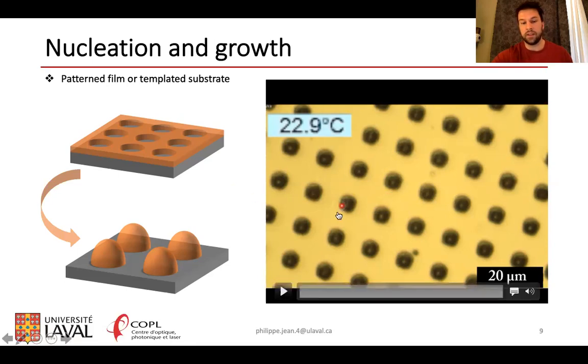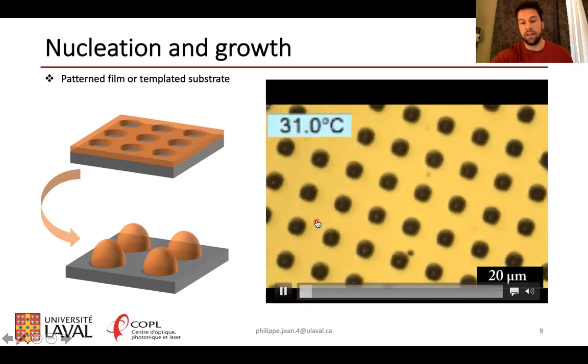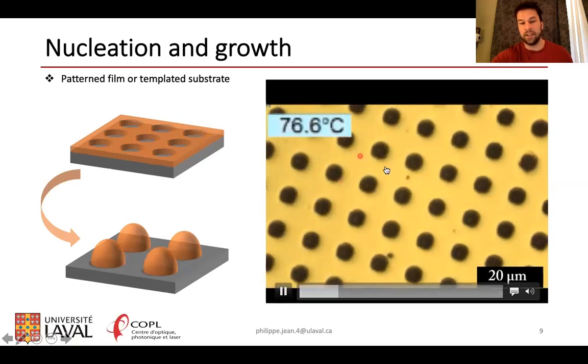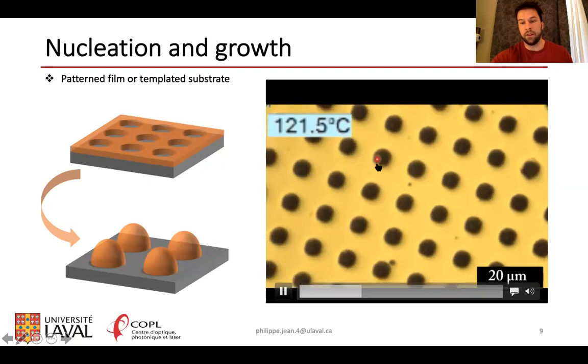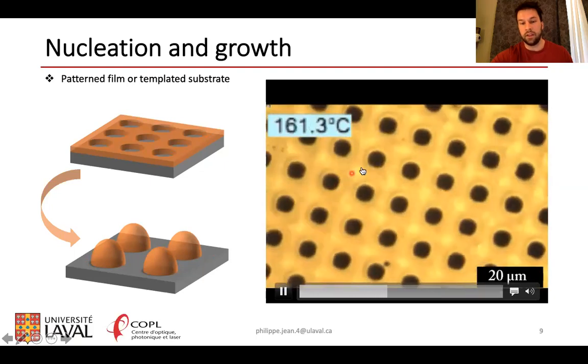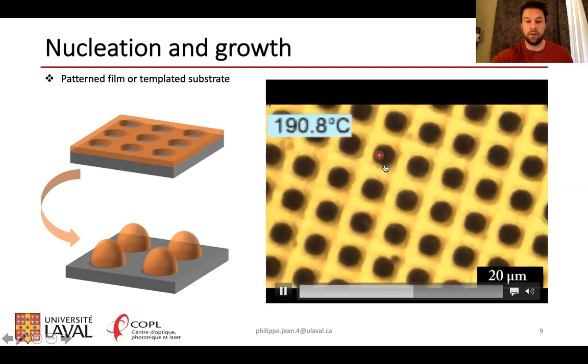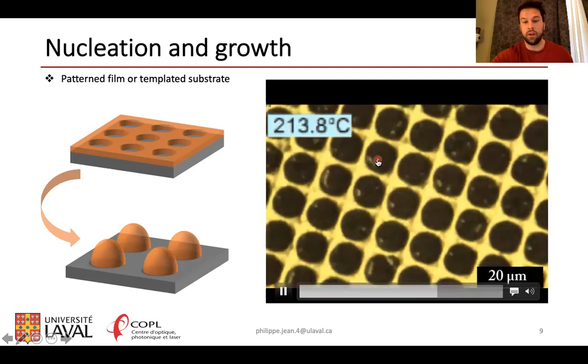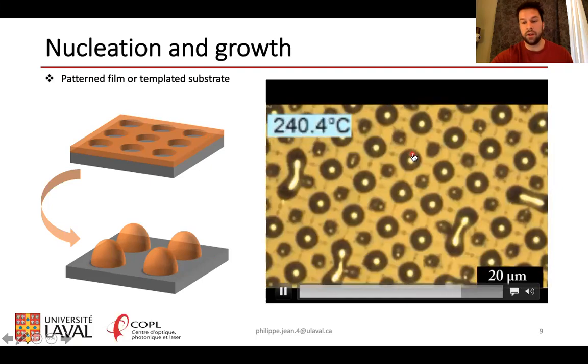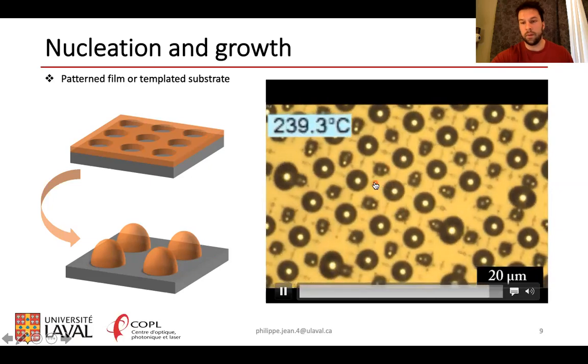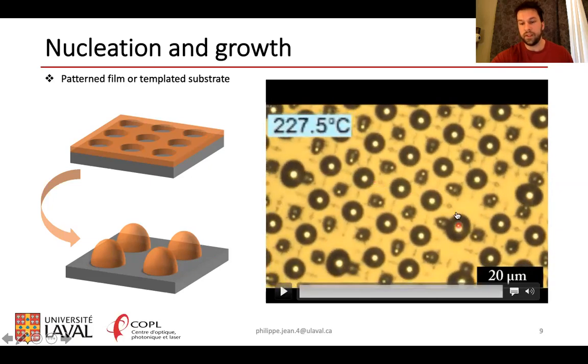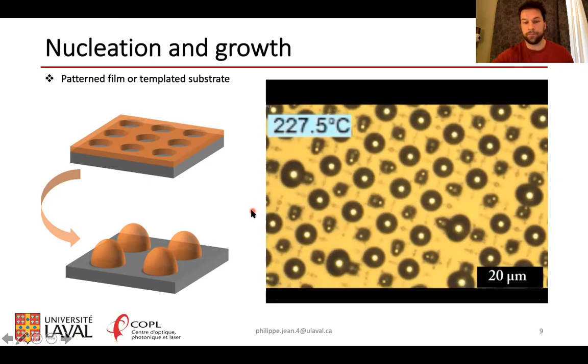And this is what we can see on this video here. Again, the glass is yellow and the small black dots are silicon pillars. And you'll see that holes will form around the silicon pillars and will grow, resulting in well-arranged droplets of relatively uniform size and shape. You can see that there are some defects, but overall, the size and shape are uniform and well-arranged.